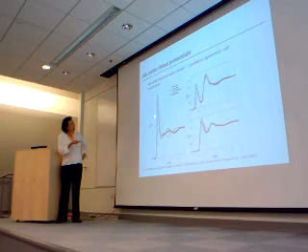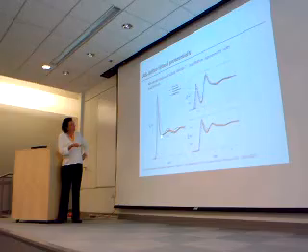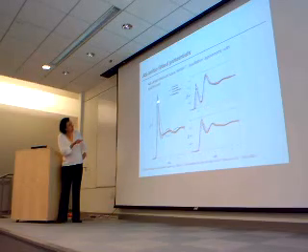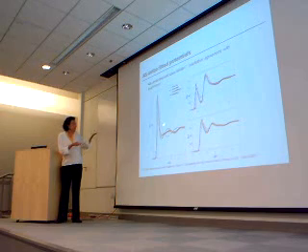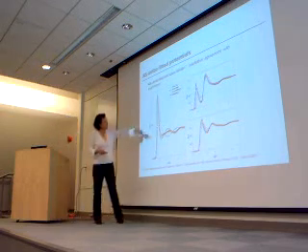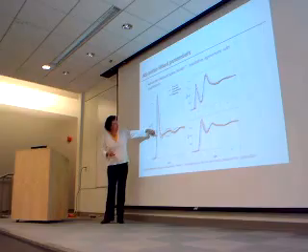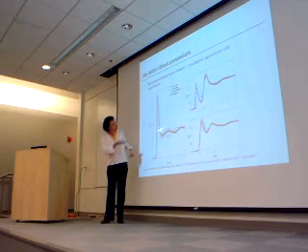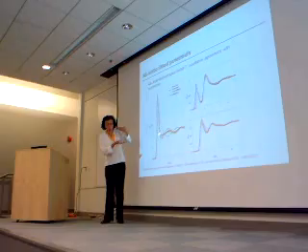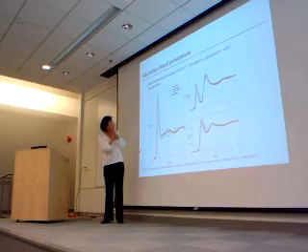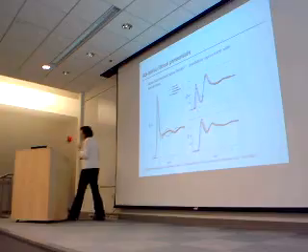This is a plot of the oxygen-oxygen correlation function. This is experiment, the black line, and the maroon and brown lines are obtained with different types of fitted potentials. And you see that you can actually reproduce the experiment quite well, at least with some of the potentials. There are different curves here, and the blue curve is fitted only to a certain amount of data. The point the authors were making is that you need to go to a very accurate fit to reproduce the results quite well.